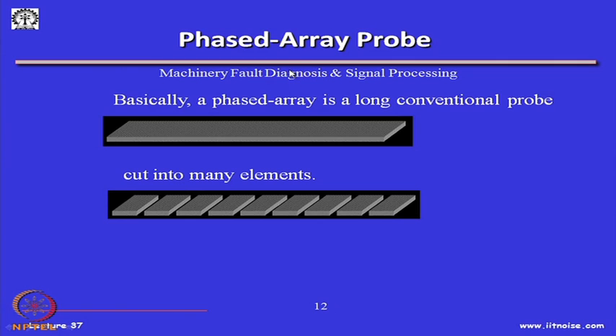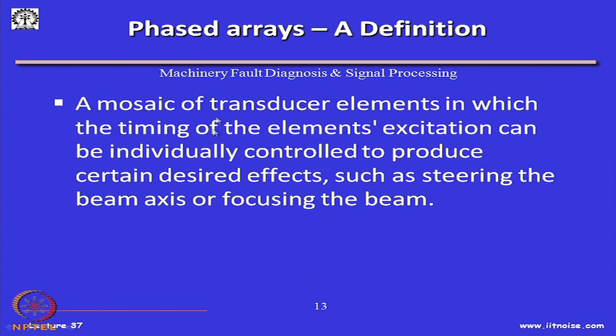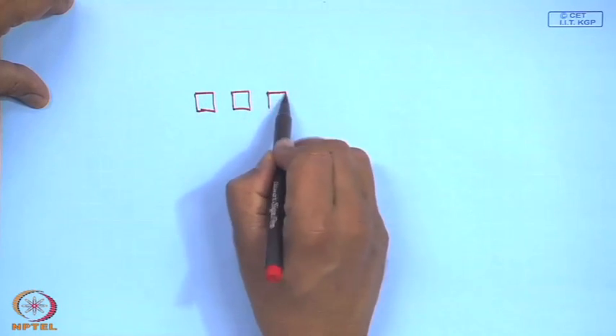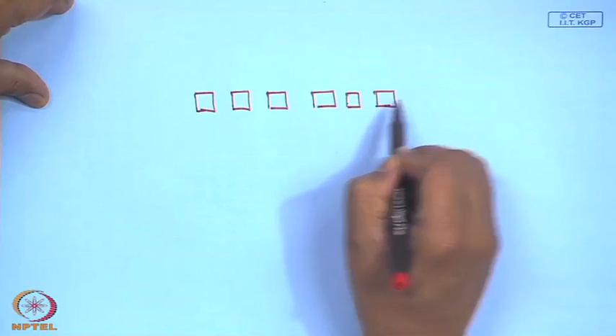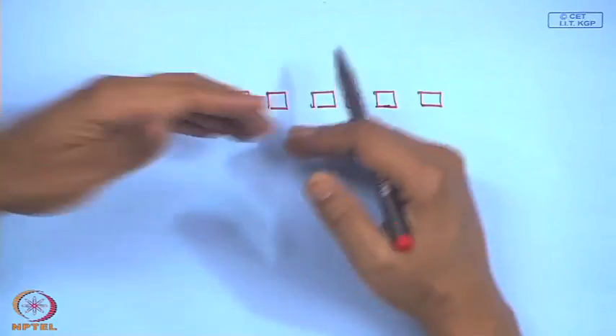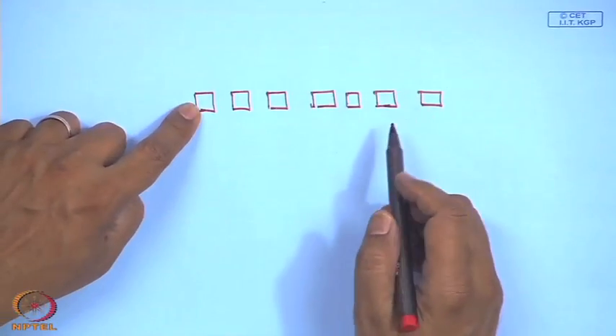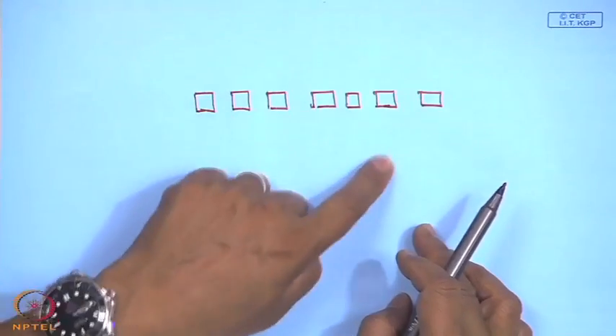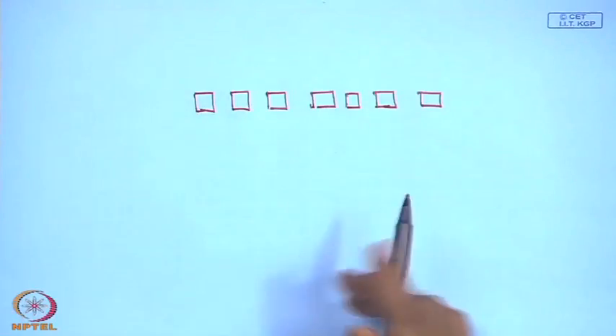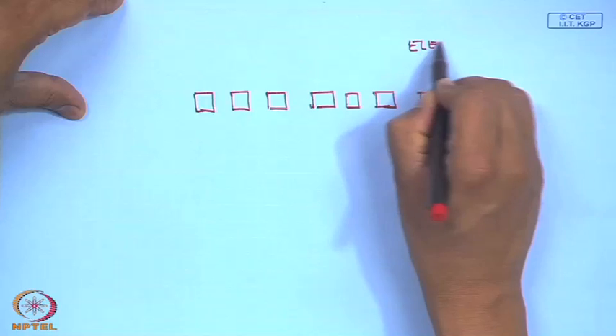So, recently what has happened is, basically a phased array probe has been made. It is basically a long probe, which is cut into many different piezoelectric elements like this, and phased arrays are those in which the timing of the elements' excitation can be individually controlled to produce desirable effects such as steering the beam axis or focusing the beam. So, through an electronic timing of these piezoelectric crystals, they are equally spaced though. So, I can excite them in one go, so all of them will generate ultrasonic waves, or I can excite this earlier than this. So, then the flight time will be different, and then I can steer them or I can converge them. So, all these operations are possible through an electronic controlling mechanism.